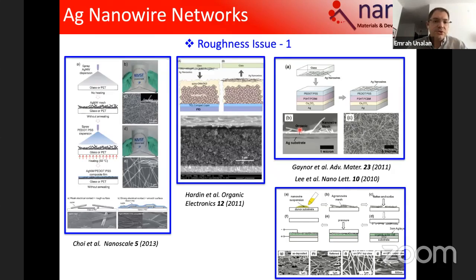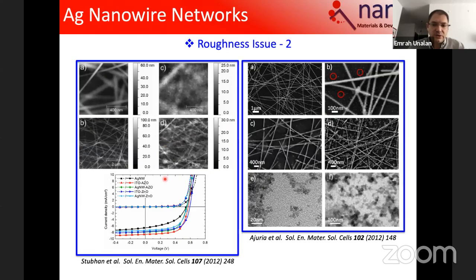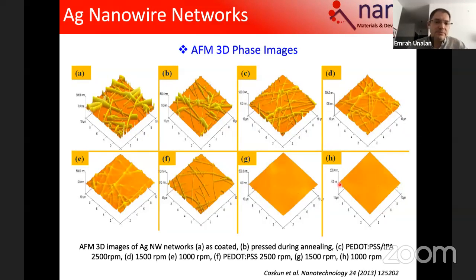When we look into the literature, people tried putting polymers, putting nanoparticles to minimize this roughness, or doing a stamping process to get rid of this roughness. And as you see, in some other applications, people put ITO particles or zinc oxide particles to planarize the surface. So we said that, okay, putting ceramic particles, putting an extra material works. But since we have PEDOT:PSS for the hole transport layer, why don't we engineer the PEDOT:PSS layer thickness, and then we can use it as a monoblock hole transport and charge transport layer as well.